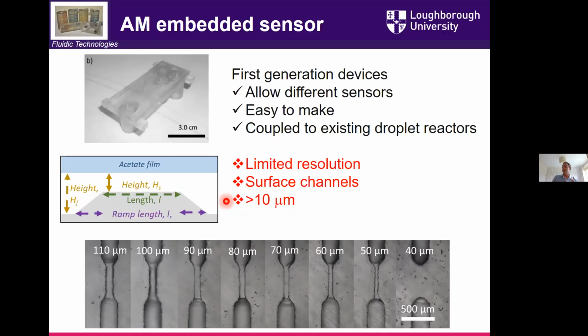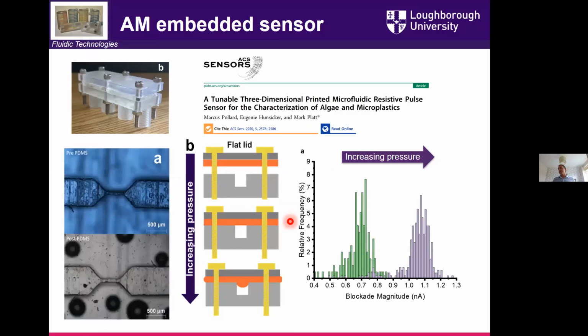But as I've hinted at, or mentioned, that they had limited resolution. We couldn't make features incredibly small. They had to be on a surface, and both of those really meant that we couldn't measure really anything smaller than 10 microns. And so that, whilst that might be applicable for some emulsion droplets, it didn't really allow us to interrogate yet the smaller droplets and the other materials that we might be making. And so Marcus was the next PhD student that came in to look at this. And this was work that we just managed to get out while in lockdown, which talks about this, if you like, our second generation. So we're not changing the SLA process here.